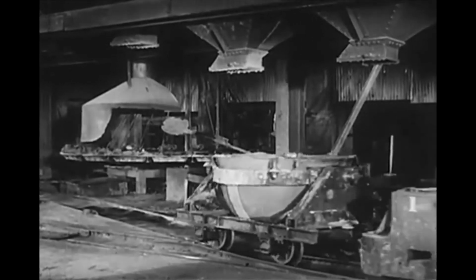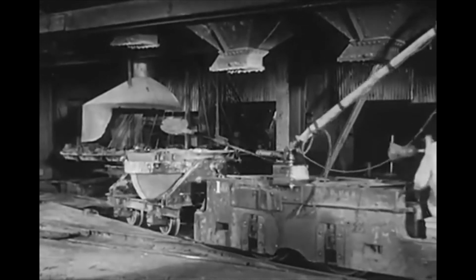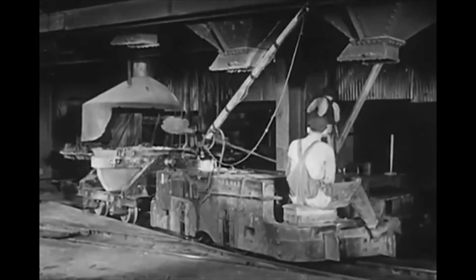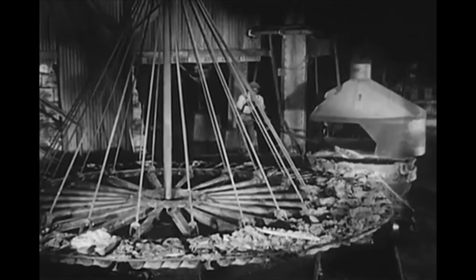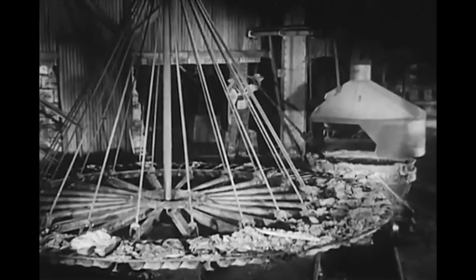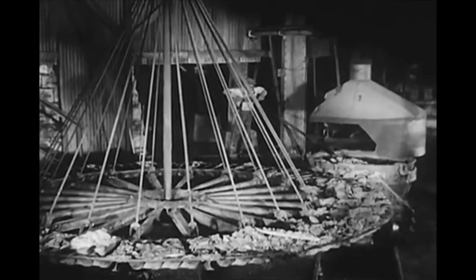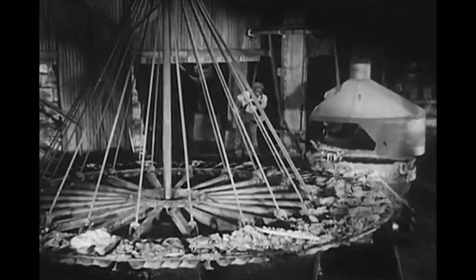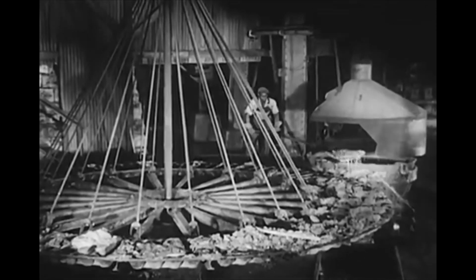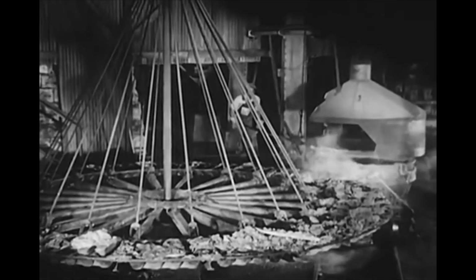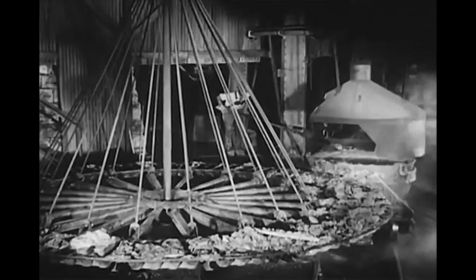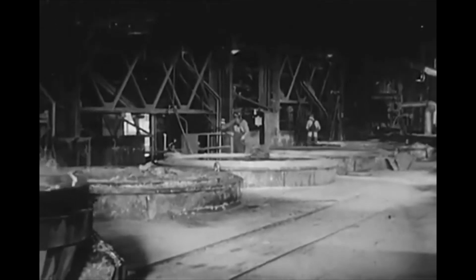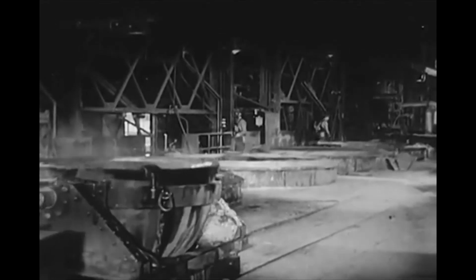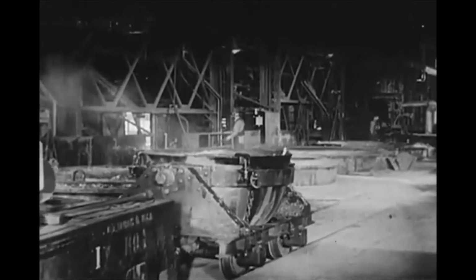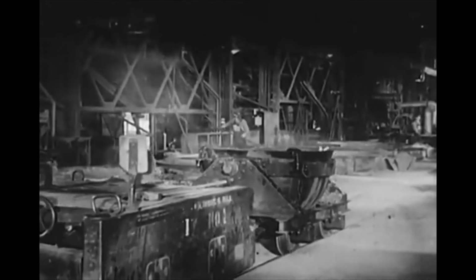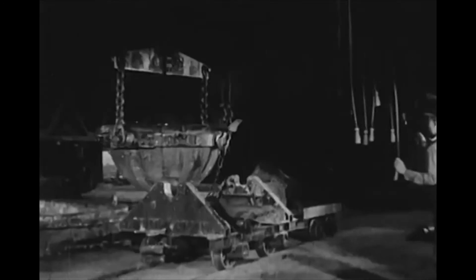This, after processing in the refinery, yields 150 tons of refined lead suitable for market. From a furnace, the lead is taken to a drossing wheel, where part of the dross is removed. Dross, containing such impurities as copper and nickel, along with a high percentage of lead, is skimmed off with a large ladle. It's poured into molds to form rough pigs, which will again be run through the blast furnace to recover their lead content. After this preliminary skimming of the dross, the lead is taken to the refinery for the further elimination of its impurities.